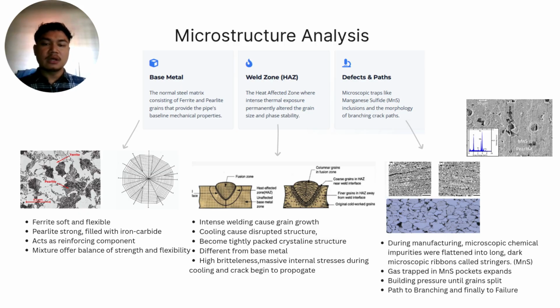And this will continue to crack propagation. This mechanism will be explained from stepwise cracking and branching. The first one, the gas will be trapped, as I explained, in the manganese sulfide pocket, expands, and it will build pressure until the grain splits, creating a stepwise crack. The path is a crack crawl along weak grain boundaries. Then it will cause branching as path growth. Instead of a clean break, a tree-root network of tiny cracks forms, and it will cause, lastly, the total failure, burst of the pipeline system.